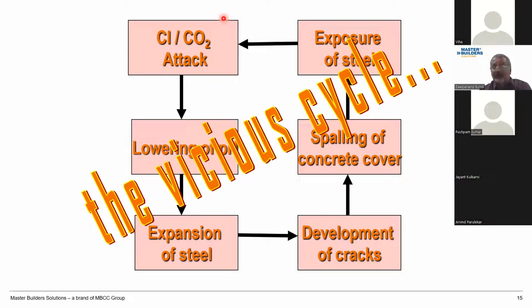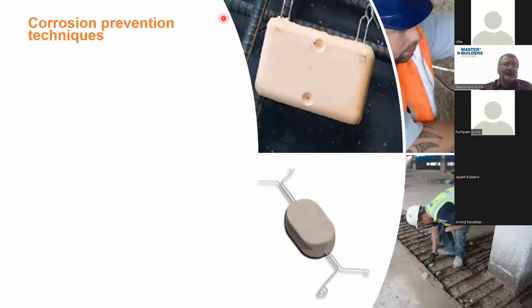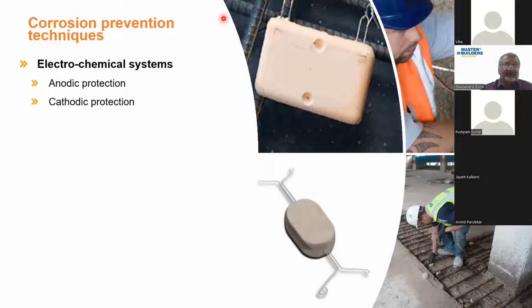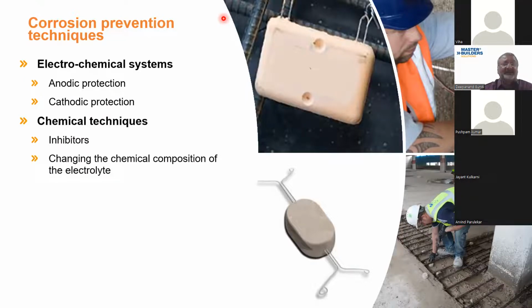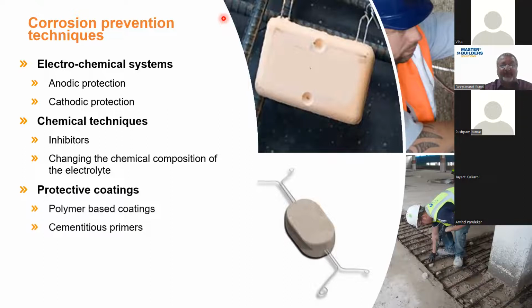The protections vary. Corrosion prevention techniques, you can talk of electrochemical systems, like anodic protection, cathodic protection, and anodes that are very easily available nowadays. Anodic protections are already established in the market. In terms of chemical techniques, you have inhibitors that are either mixed into the concrete or applied on the surface. You can change the composition of the electrolyte. You have protective coatings available today, which are polymer based coatings, cementitious based coatings, and zinc rich epoxy based coatings.